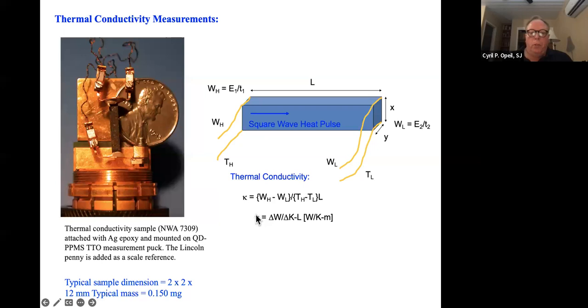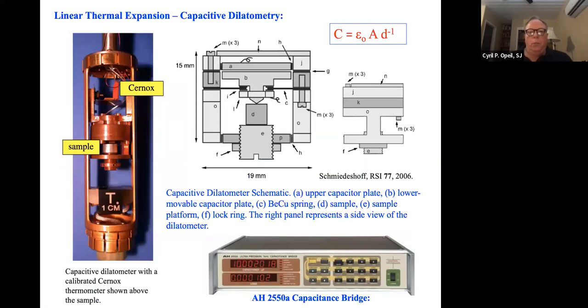Kappa, which is the thermal conductivity, is essentially the ratio of the heat, the watts, divided by the temperature and the length per unit length. And so we get some data from this. I want to say something about linear thermal expansion. And this is a technique which is, I would say, for people in meteoritics, or even in physics in general, a fairly rare technique.